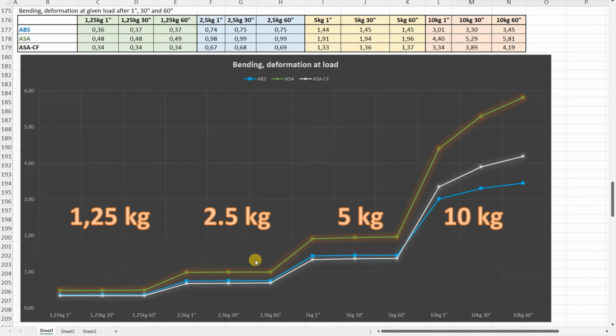Where the ASA was the weakest in this test, but with the ABS and ASA-CF, interesting smaller initial deformation we can see with the ASA-CF, but look at this, under 10 kilograms, significantly more deformation, not only the initial, but even after 1 minute under 10 kilograms. Of course you don't want to use the parts under these loads, but it is good to know about it.